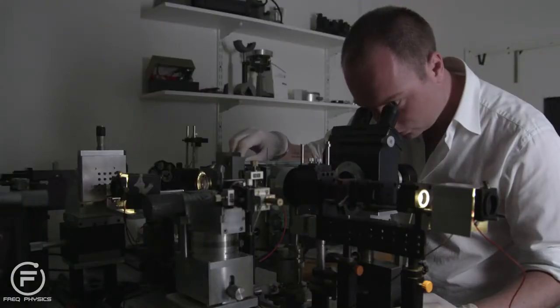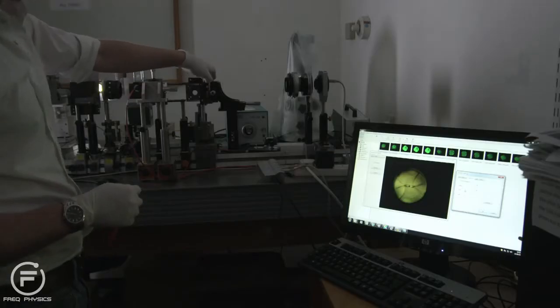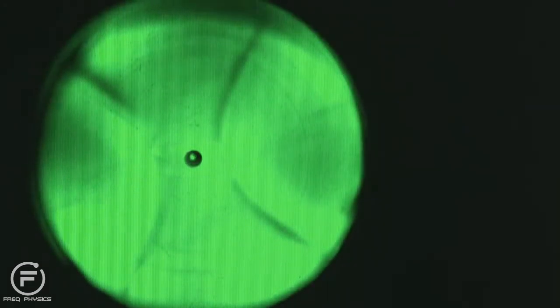If flat silver is placed into the scatterometer, all we would see is reflected green light. If we pattern the silver surface with a grating, then what we see on the screen is some missing portions of light — the light has gone into exciting surface plasmons.